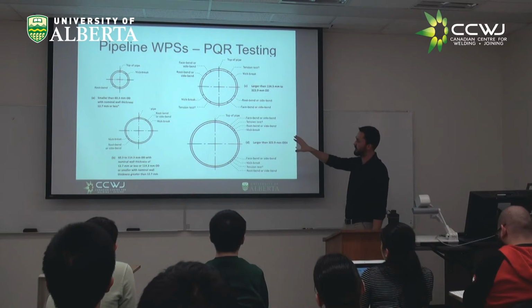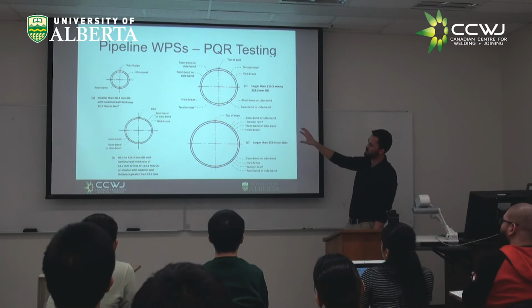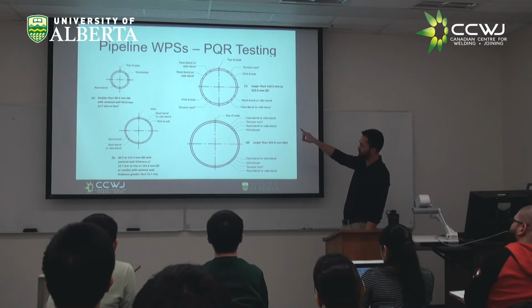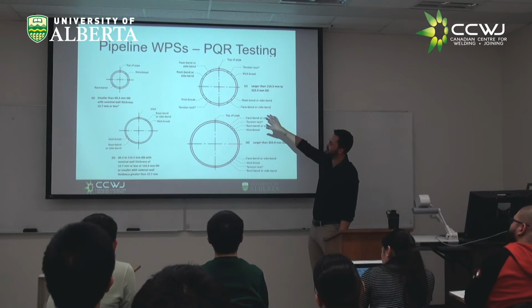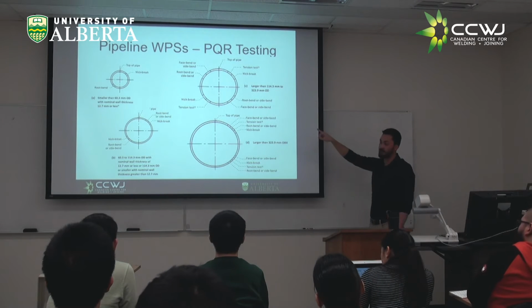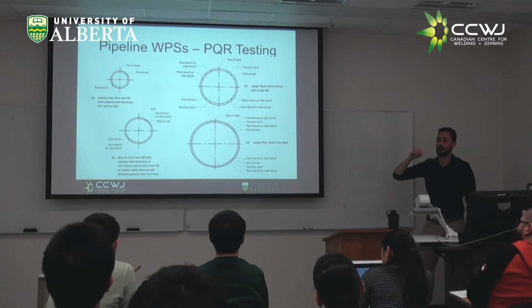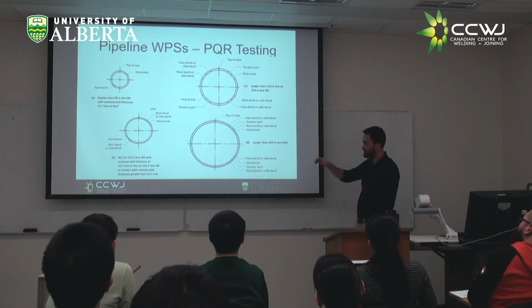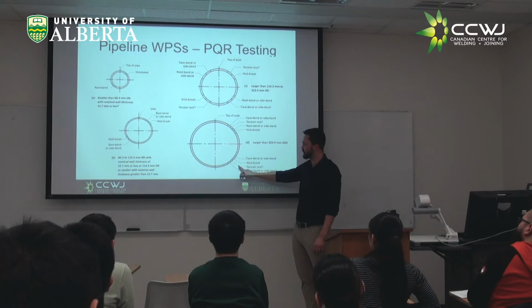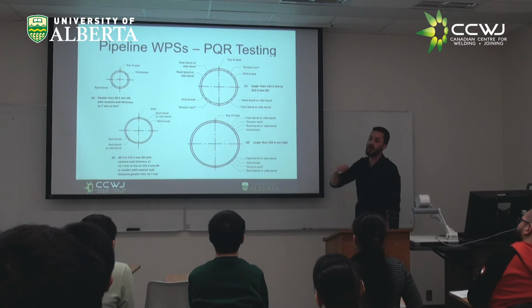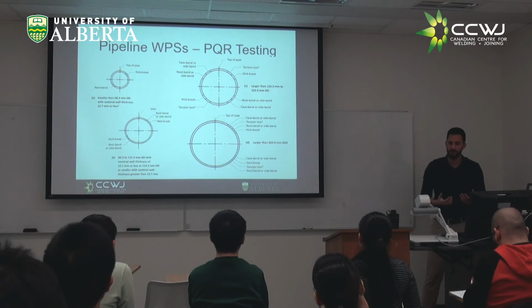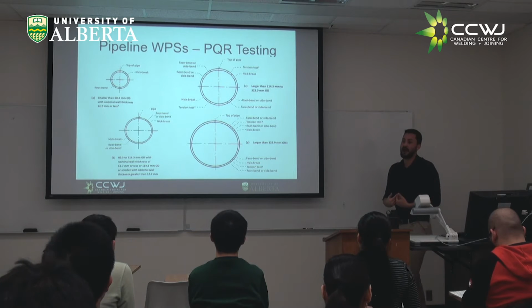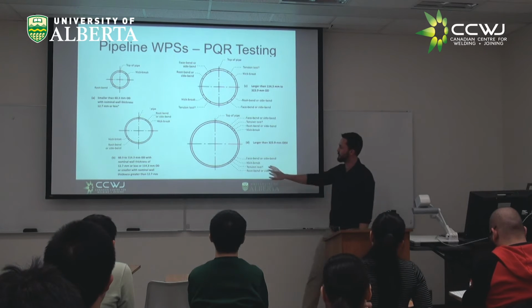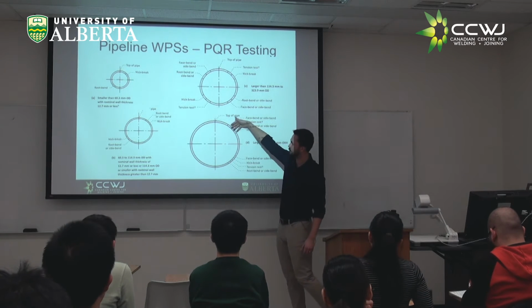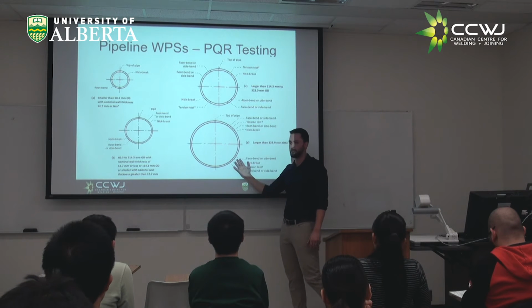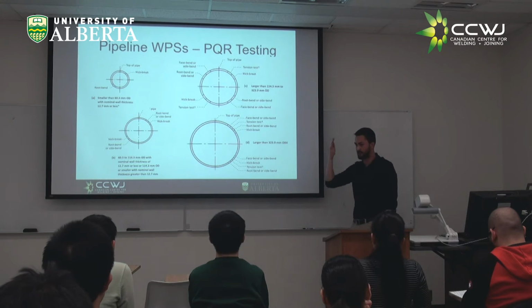And Z662 is very good about this. And all the codes will show you in a different way, and I'll show you a little bit later the structural side of this. But it'll show you exactly where you need to do this. And the reason for these selections has a lot of intention behind it by the code designers, essentially wanting you to extract samples from your pipe at places where you're likely to have the worst properties, right? So when you're down here, you have some of the ones where you should have good properties, but you also have them from down here where you might have some of the worst properties as you're coming down.